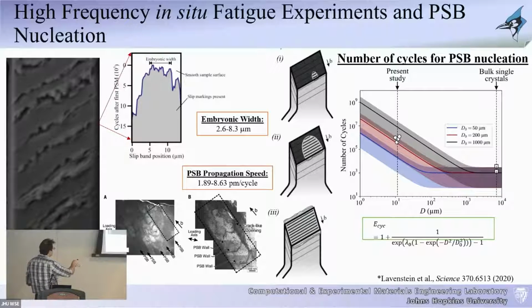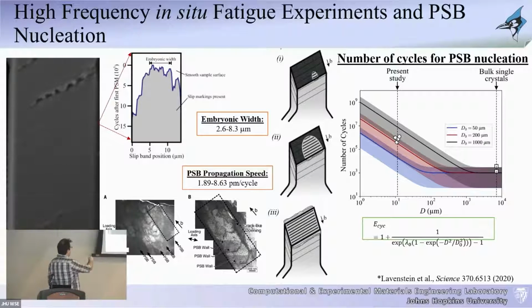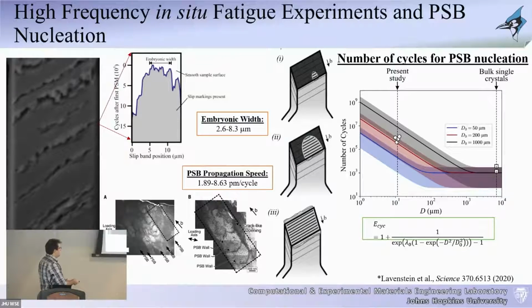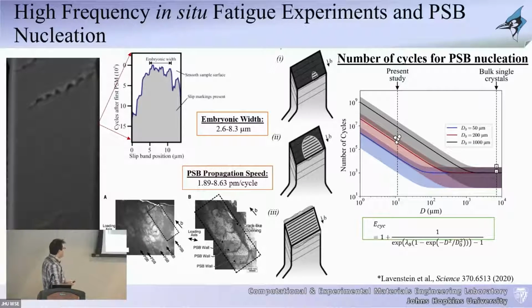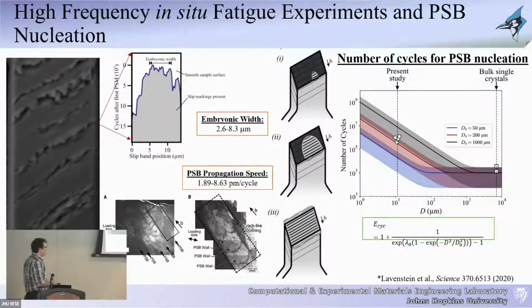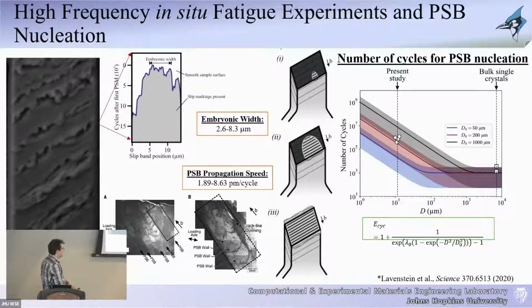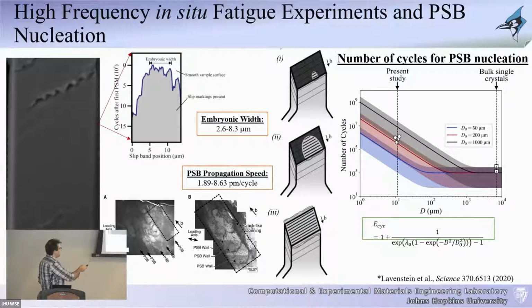In addition to that, we can actually quantify the speed as these bands form on the surface and propagate, extending to both corners of the sample. We can quantify the speed of the propagation of these persistent slip bands. In bulk experiments, interestingly, they have never been able to calculate this. One reason is that you don't really see these experiments, you don't see the evolution of them. So this was quite unique in that sense, giving us the ability to first observe it. Now, we've been able to quantify, or at least physically explain, what we think is happening in it. We still cannot see what's happening internally, but we think that the reason why you get these different sizes of embryonic widths of these persistent slip bands hitting the surface really depends on where they nucleate relative to the surface.